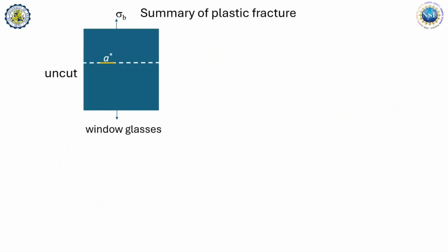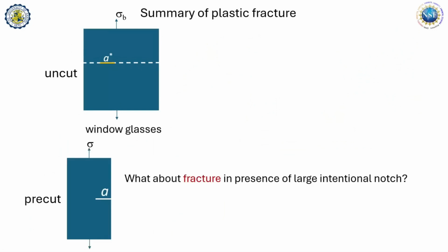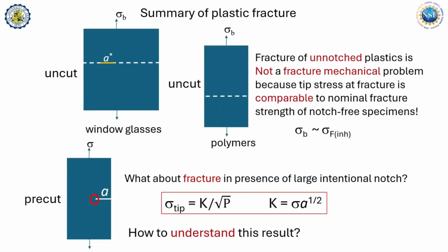So here's the summary for brittle plastics. If you have plastics, it turns out your nominal strengths are comparable to the true strength, which we measure from the tip. And therefore, what you learned is that the fracture mechanics in presence of a large cut is dictated by how the stress builds up at the tip.